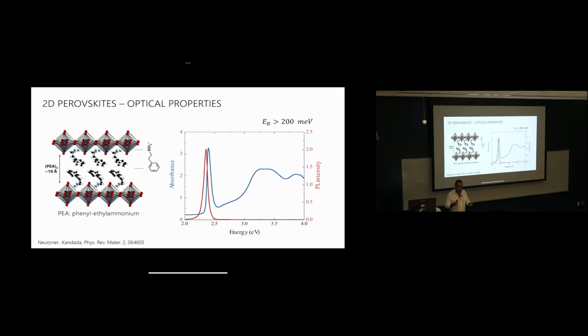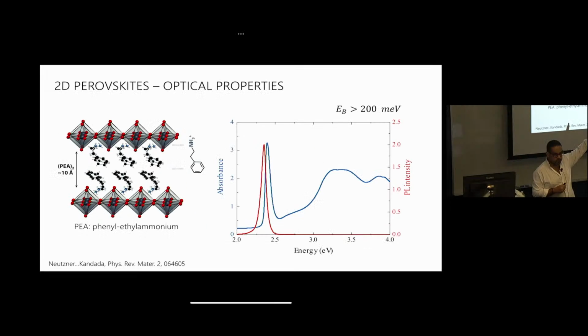They're Coulomb-bound electron-hole pairs. In the regime that we're talking about, you excite an electron from the valence band to the conduction band. You leave behind a hole. There are very strong Coulomb interactions that give rise to hydrogenic-like bound states. And here's the origin of that series, that Rydberg-like series. And so these are very strongly bound excitons.